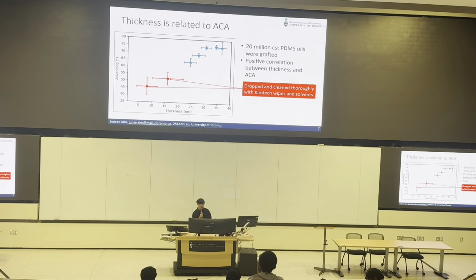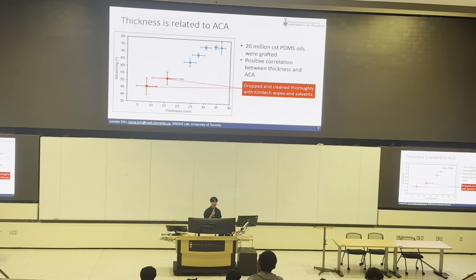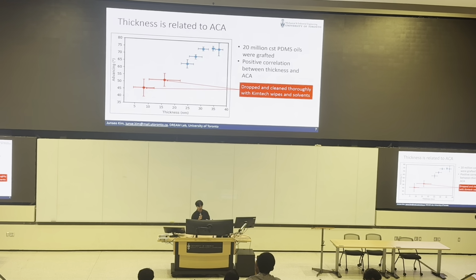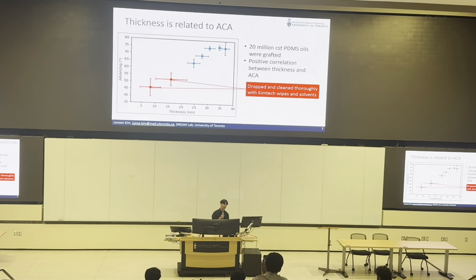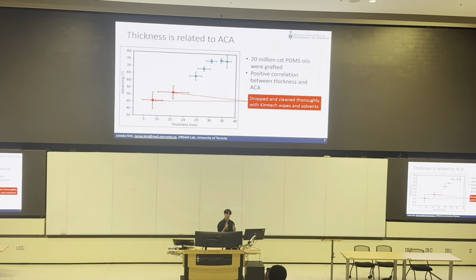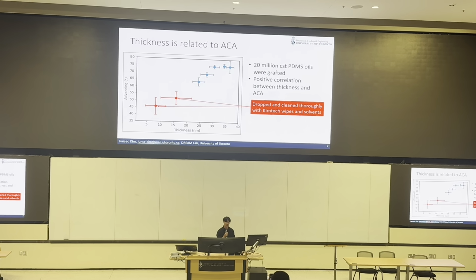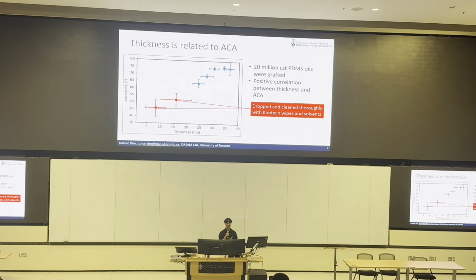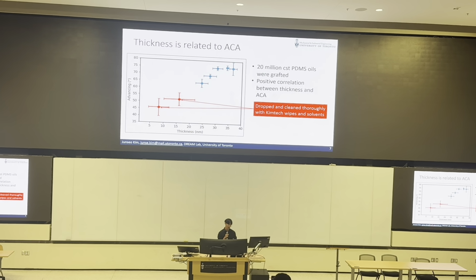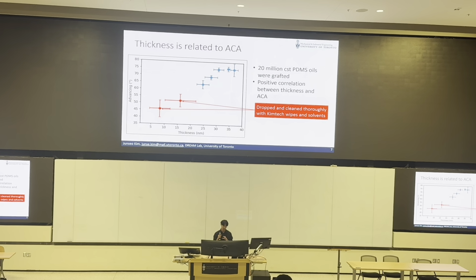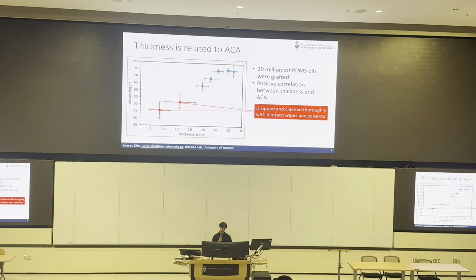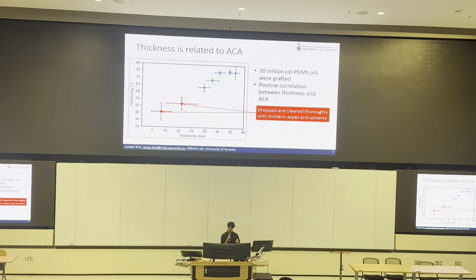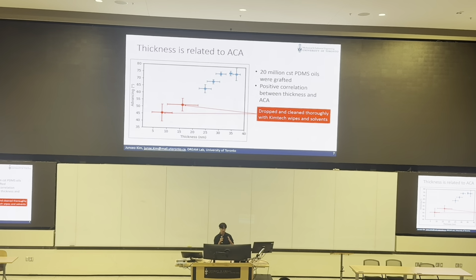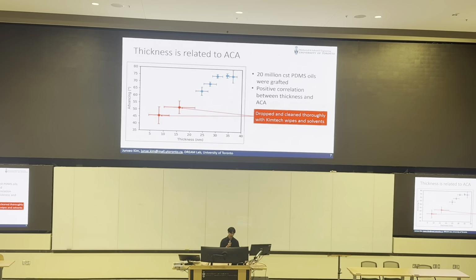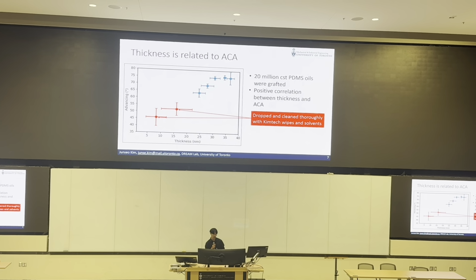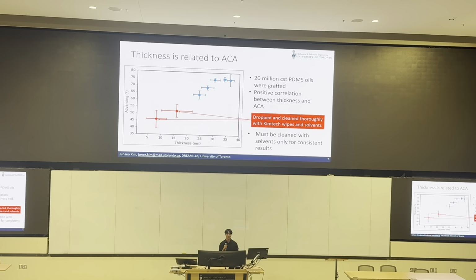Because of that, I cleaned them very thoroughly with the solvents that I used, but on top of that, I cleaned them very thoroughly with these Kimtech wipes, which I was using, but I wasn't being very thorough with them. I was being gentle with them, but with these contaminated ones, because I wanted to clean off all the contaminants, I was super thorough. After that, I saw a huge decrease in the thickness. But then the advancing angle also decreased, which supported my hypothesis that thickness is related to the advancing contact angle, but we can't have that because we want consistent results.